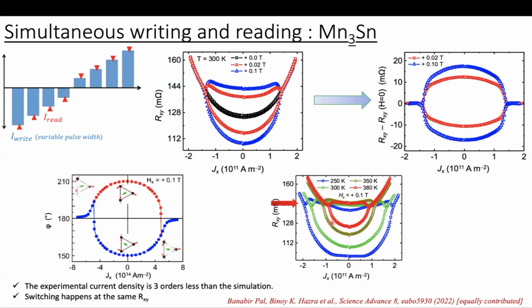Another most important observation from this experiment: we performed the switching experiment for different temperatures, 250, 300, 350, and 380. As expected, as we approach the Néel temperature of this system, which is 420 Kelvin, the current density decreases. But the Rxy value remains the same for all these temperatures. Whether it's 250, 350, 300, or 380, the switching happens at a particular Rxy.